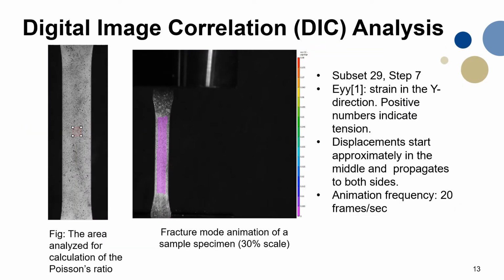This is the digital image correlation, DIC, used for the analysis. In this case, we have selected a subset of 29, which means the tracking area of the dots for the DIC was 29. The larger the area, the larger the tracking area, but also the less uncertainty. And we have selected a step of 7, which means for every 7 data points, the software took the average and used the average data for the calculations in order to save computational time. And for the Y label here, we have EYY, which means the strain in the Y direction, so positive numbers indicate tension here.